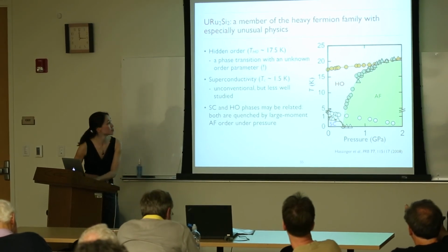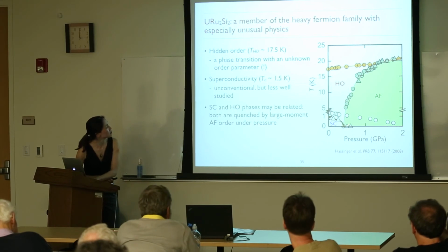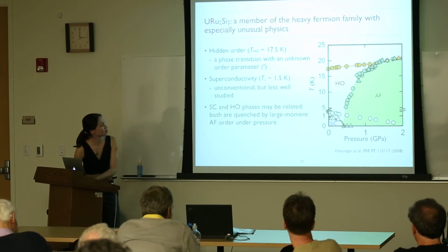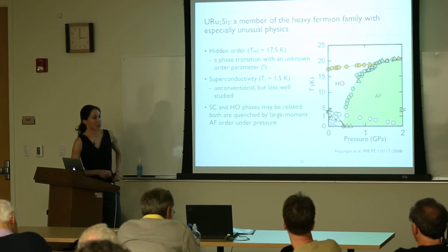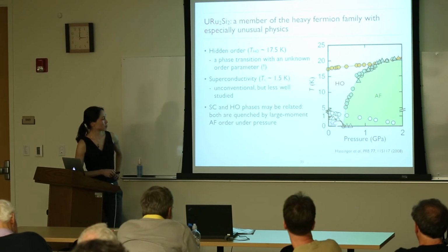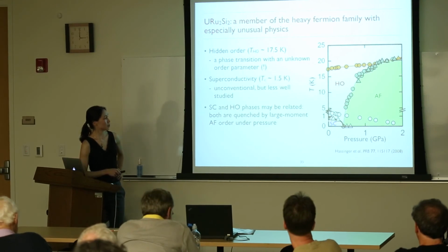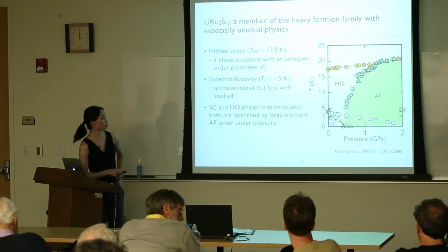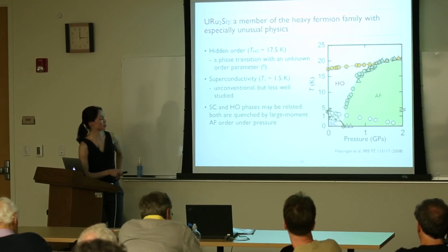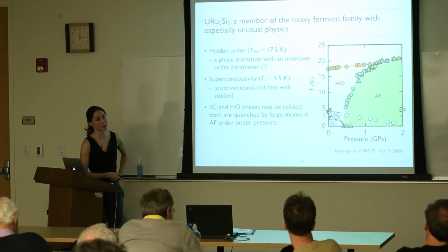Wait, Elizabeth? Yes. You have the black line is the superconducting, this guy? Yes. And does that data come down and hit zero at the antiferromagnetic boundary, or does it run into the antiferromagnetic boundary? I think there's some argument about this. I don't think that the transition temperature runs into the antiferromagnetic boundary, but there's some debate as to whether TC becomes zero exactly where the Néel temperature becomes zero, or if this dome actually sort of dies off before then.